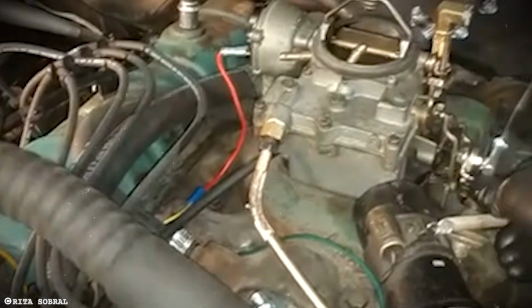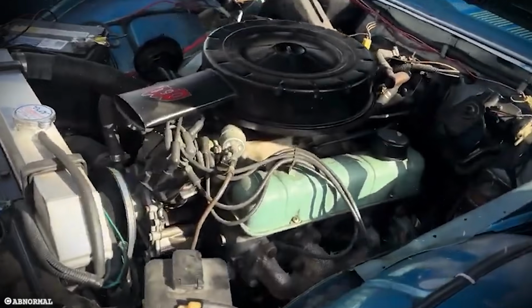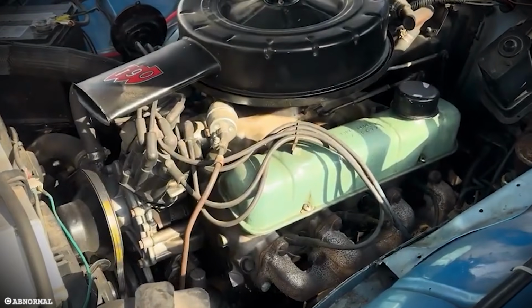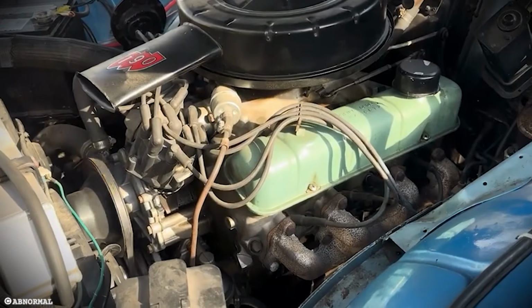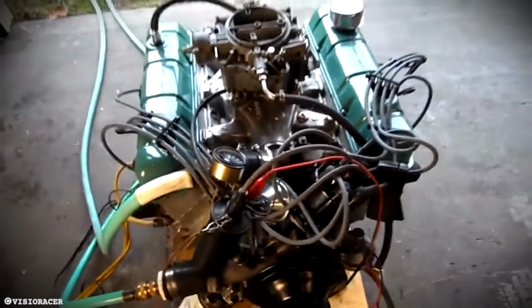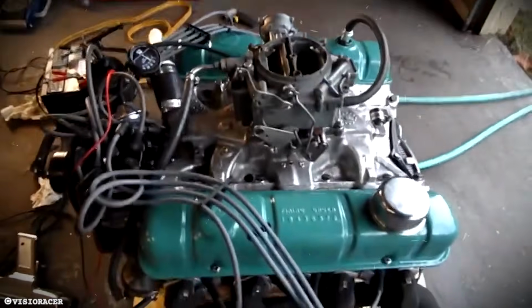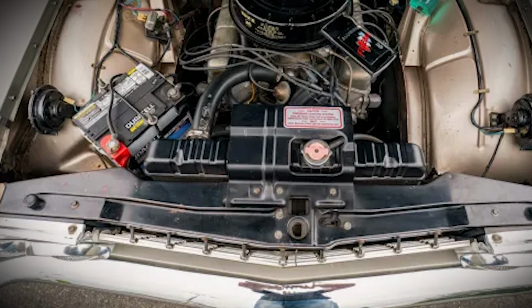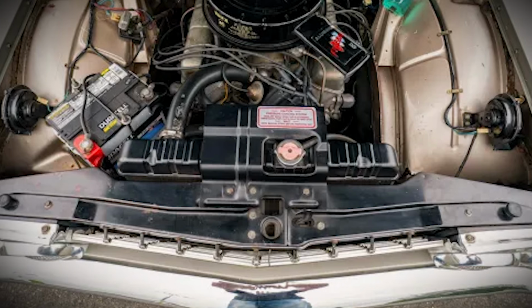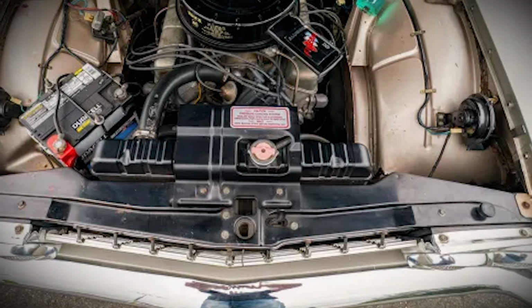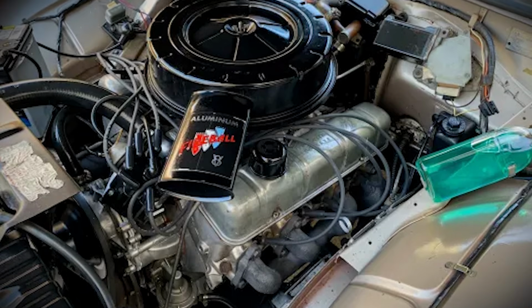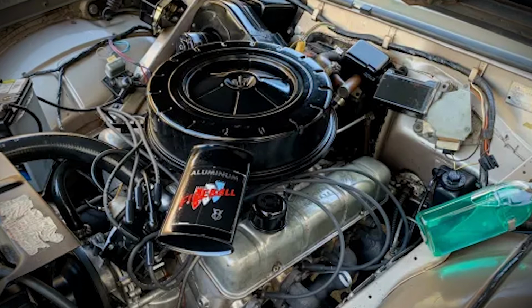The cylinder heads were equally complex. The valve seats and guides needed to be made from special austenitic iron that wouldn't work loose as the aluminum expanded and contracted. They had to be installed with an interference fit precise to 3/10,000ths of an inch. Too tight, and the aluminum would crack. Too loose, and they'd fall out after a few heat cycles.